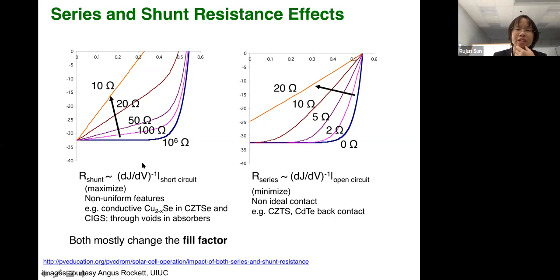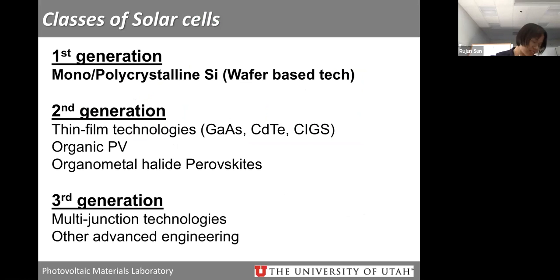Some materials make this very easy to achieve, but for the shunt resistance, for example, if we have some conductive phases or some voids in the absorber, it will connect the front electrode and back electrode together directly, so it will leak. For series resistance, we want only the contact electrode with the absorber, but for some materials there is not an ideal contact. The back contact is in most cases like a Schottky contact, so this will increase the series resistance and decrease the fill factor, and thus the efficiency. So we have reviewed the ISC, VOC, and the fill factor.